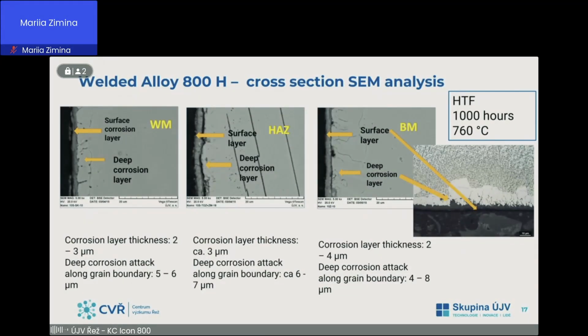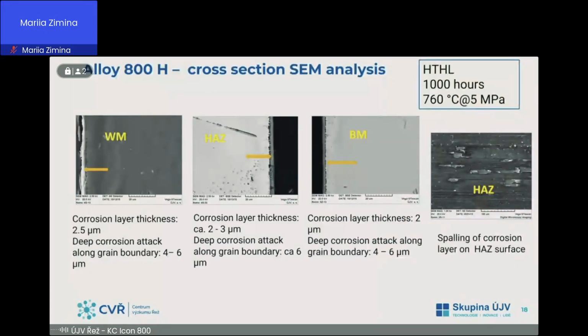On the cross-section of the samples, weld metal, heat affected zone, and base metal, a compact surface layer made of chromium oxides was observed, and under this layer corrosion attack along the grain boundaries was found. For the samples exposed in the helium loop, the corrosion was similar to that observed from the surface, also including the spalling on the heat affected zone.